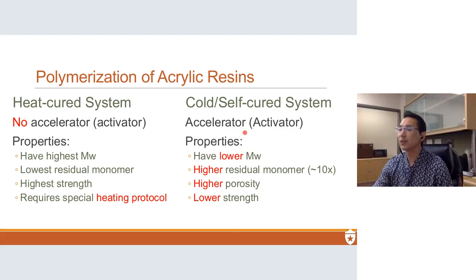But in this situation, an activator is needed to get the benzoyl peroxide to form a free radical, okay? Because there's not enough heat there. The reason why this is not as widely used is because they tend to have lower molecular weight, just not enough energy to drive the polymerization. They have a higher residual monomer because of that, about 10 times higher residual monomer. They also have higher porosity, mainly because of the mixing, and they do have lower strength.